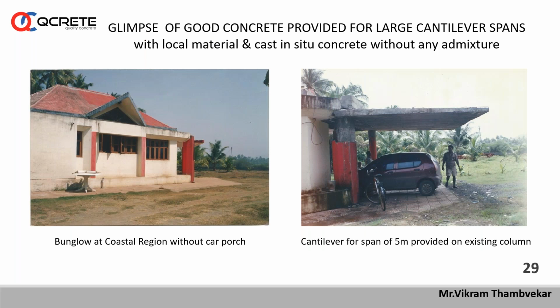See, here I have purposely kept some pictures of used fresh concrete, which we used for some projects. Why I have kept this picture here is because all this concrete we prepared at site, in situ concrete, with the local material and without admixture, because admixture was not available in some rural and coastal areas. So we made fresh concrete with what material was available.